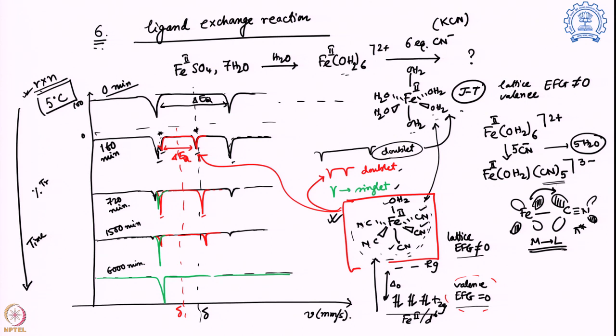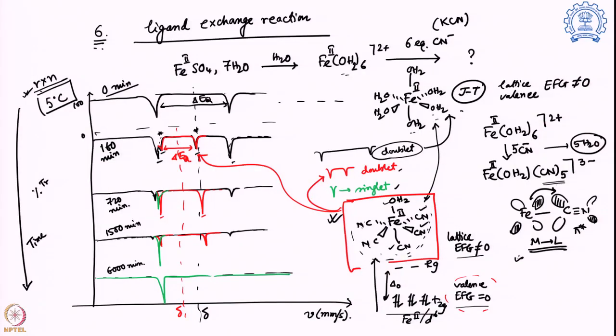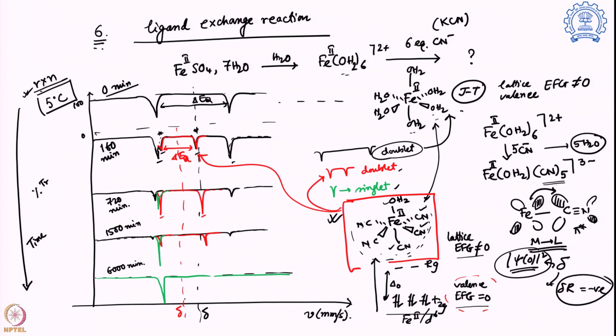So this back bonding will happen, electron density will move out, and as we have discussed in the earlier segment, as you are moving the d electrons out, you are cutting down your d electron density, cutting down your shielding effect for the d electrons, and the s electron has more chance to see the nuclei. And if that is happening, your psi zero square value is increasing, and that is going to affect the delta value, which is dependent on this, and the delta R value, which is negative in nature. So multiply those two together, I am going to shift to a negative value if my d electrons are going out of my sample. And that is exactly what is happening, my d electrons are moving out and I am having a delta value further shifted.